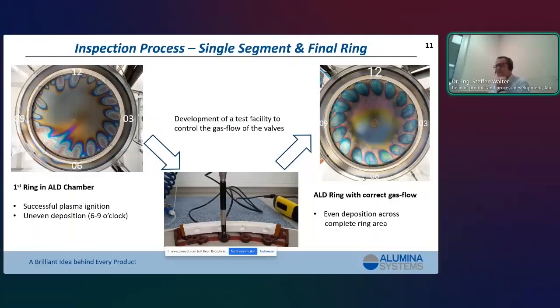This is now a very important step, the inspection process of such single segments and final ring structures. Stefan told you already, this was one of the first ring structures on the left-hand side of such an ALD chamber. So the ring is here mounted on the lid, and it was successfully processed in a plasma ignition, so that was 2022. But what we see now on the lid is that between 6 and 9 o'clock we have this uneven deposition of gas. You see this here on the lid structure, and the rest is more or less good, but we have areas that are quite uneven.